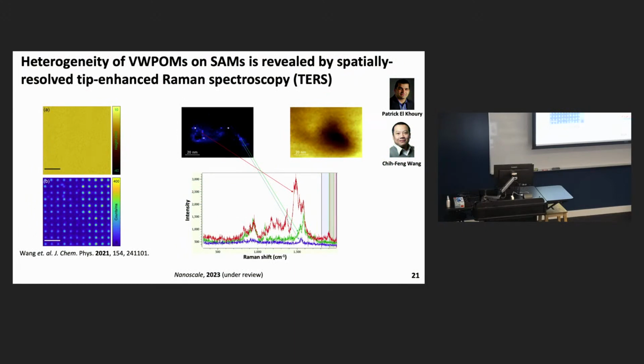Here are the results we obtained from tip-enhanced Raman spectroscopy. And the idea here was to try to understand the heterogeneity that occurs on surfaces even under these well-defined conditions where you have a monolayer with mass-selected ions soft-landed. Now, when we initially tried to obtain these spectra, it failed because we did not have significant enough enhancement. So my colleague, Patrick El-Khoury, came up with this idea of creating arrays of defects on surfaces using an AFM tip,